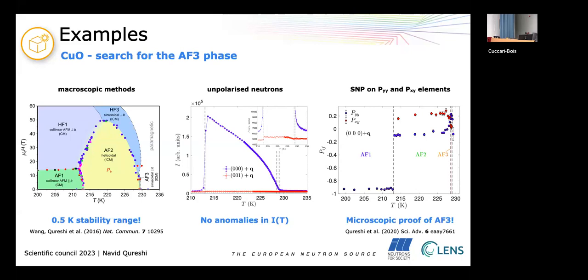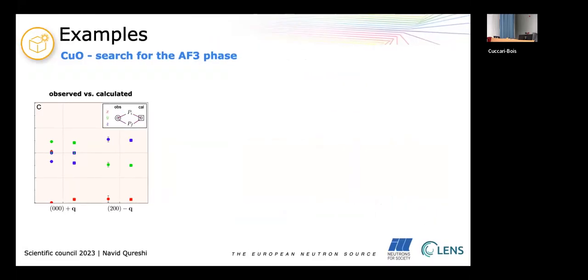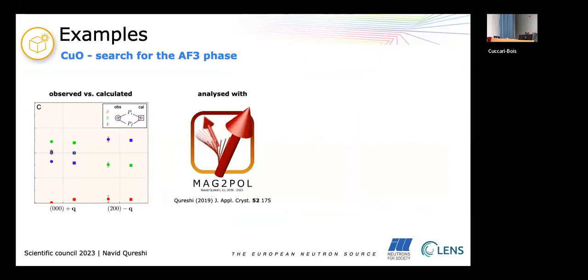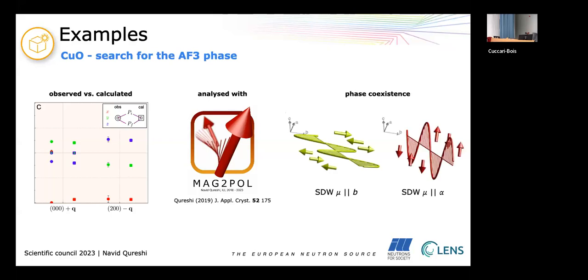At the time my collaborator who came with the crystal had no confidence in the idea. He said Navid this is not going to work, let's try another crystal. And I told him well let's at least measure overnight and let's see what happens. And this is what we measured overnight. We have this huge change at the transition between the collinear and the multiferroic structure but we also see a clear anomaly in the AF3 phase and that was the first microscopic proof of that phase in almost four decades of neutron scattering on copper oxide. So by measuring and analyzing two polarization matrices we found a model which explained the data. And this was done using Mag2Pol, this is a program I have developed to treat polarimetry data at the time and that helped a lot to revive the polarimetry community. But with time it has developed, it also does unpolarized data on single crystals and powder, also x-ray data and constant wavelength and time of flight. So what we could extract is that we have a phase coexistence of two spin density waves with different moment directions and that helped a lot to understand copper oxide globally and especially in terms of its detailed balance of energy or exchange interactions.